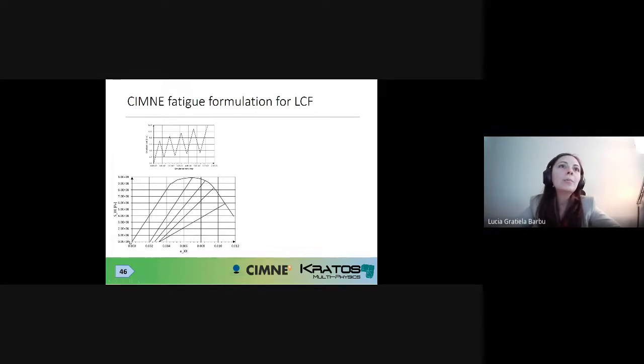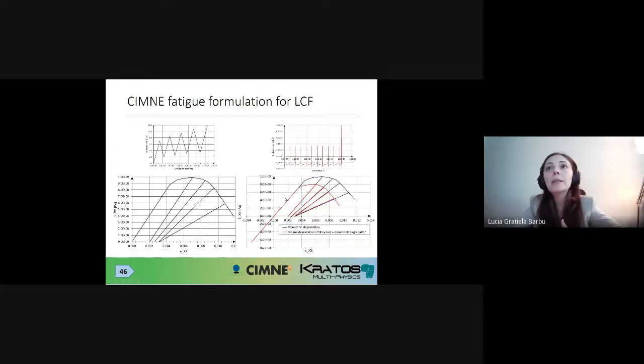And here, for instance, you can see an interesting case, when you apply this type of loading and you begin with a completely plastic behavior, then you pass into a transition zone where you have plasticity accumulated with damage, and you continue up to a point where you begin to exhibit exclusively damage, okay? This is perfectly possible with this model. And another combination where we have cyclic loading, 10,000 cycles applied, and after that we break the sample monotonically. And during these cycles, we do this unloading here, where you can see how the behavior changes from plasticity with damage, and in the end, we only exhibit damage behavior in the part where softening is obviously exhibited.